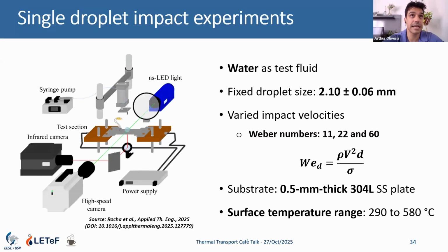To be honest, I think that may have an effect we need to consider, because the plate thickness we're using here is about 500 to 600 microns. If we take the paint used in cars, it's about 100 microns, so it probably has an effect we need to consider later.